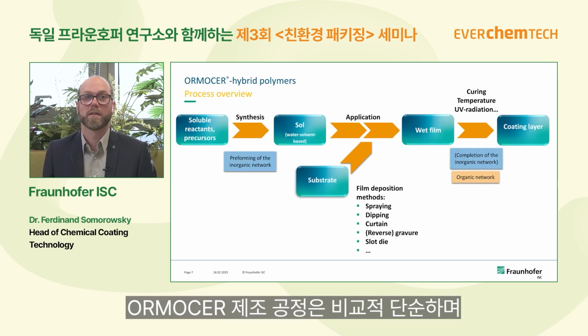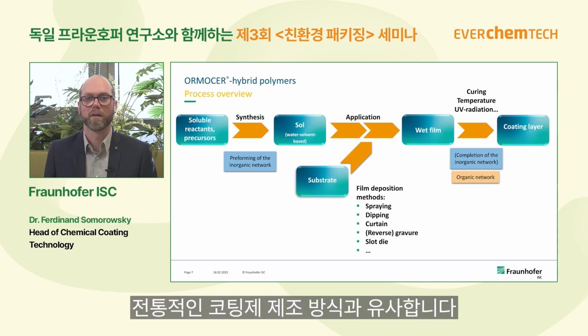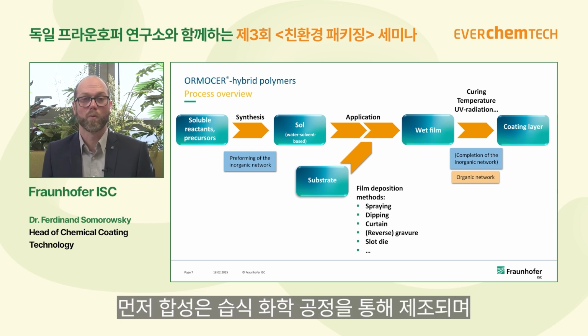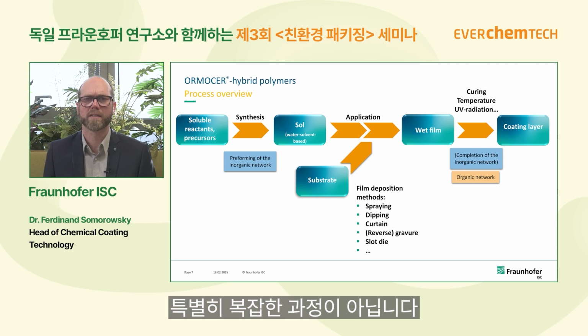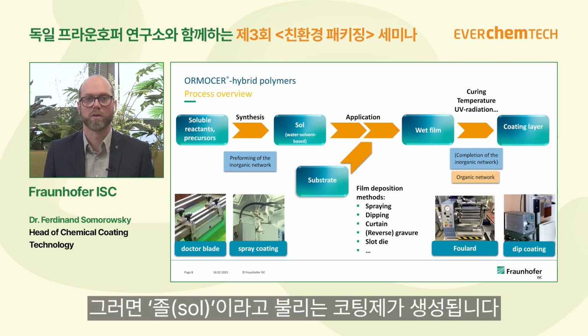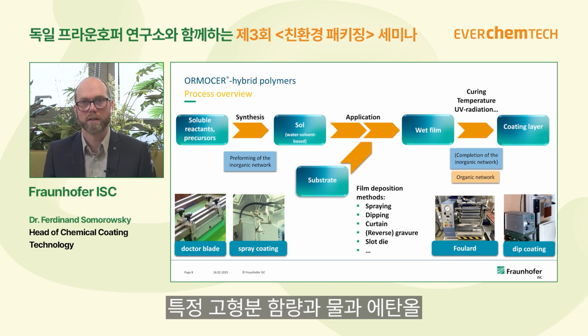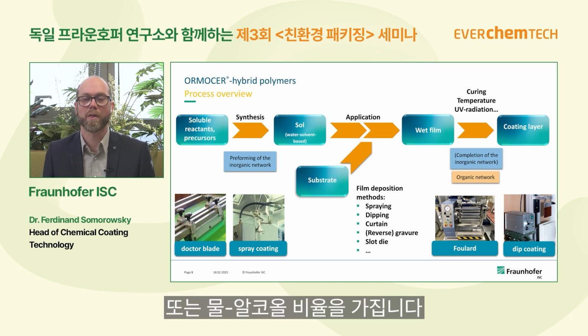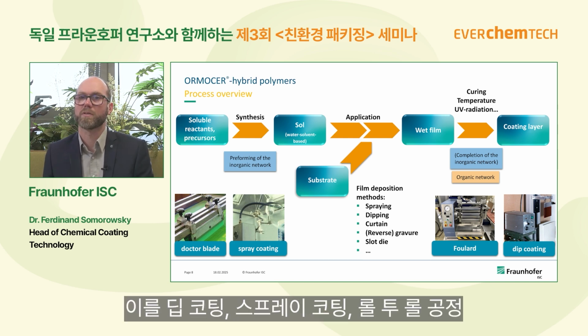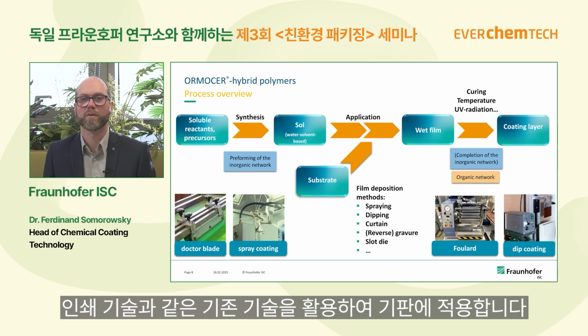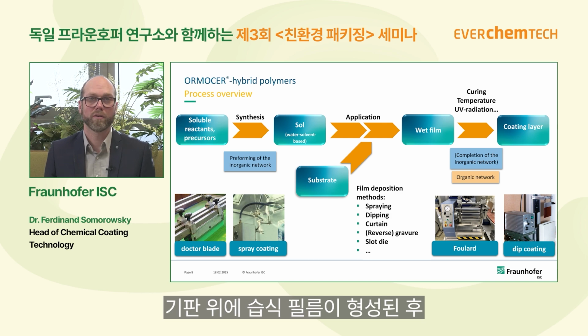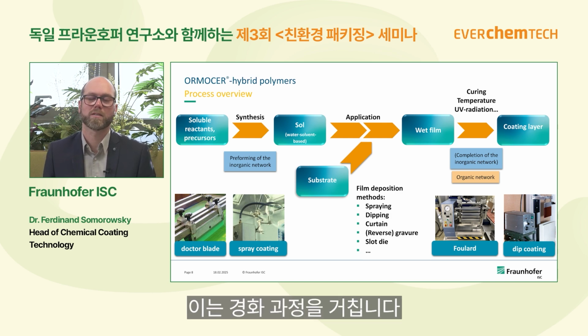The ORMOCER process is in principle very simple and comparable with classical lacquer formulation. You have the synthesis at the beginning, a wet chemical synthesis, not special, not complicated. Then we have our lacquer, or we call it sol. It has a certain solid content, and then a water and also an ethanol or alcohol-based ratio. And this lacquer can be applied on substrates with conventional methods, so dip coating, spraying, roll-to-roll processes, also printing processes. And then we have our wet film on the substrate, and this wet film has to be cured.